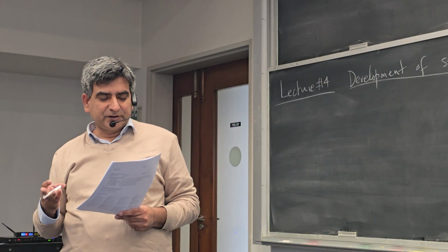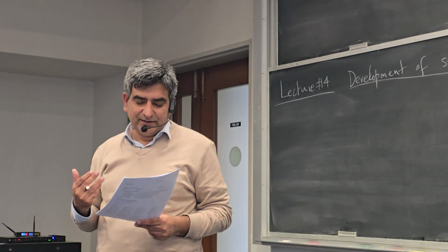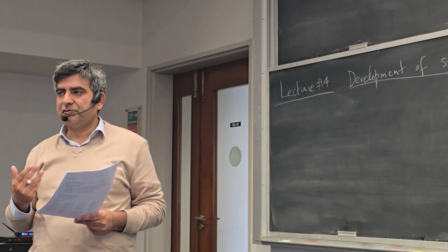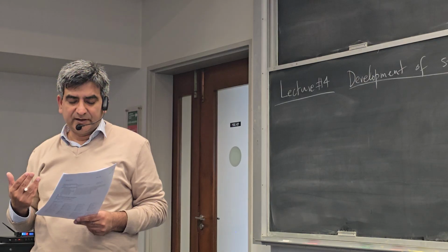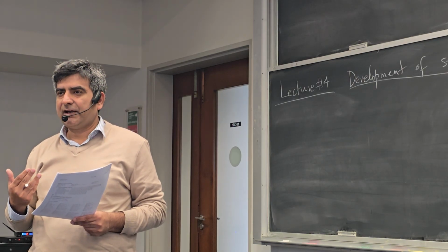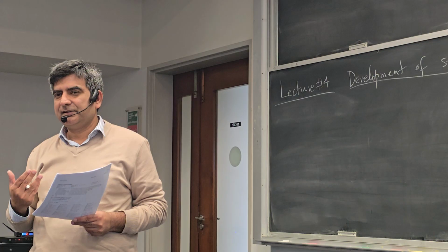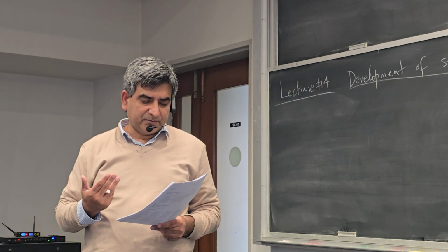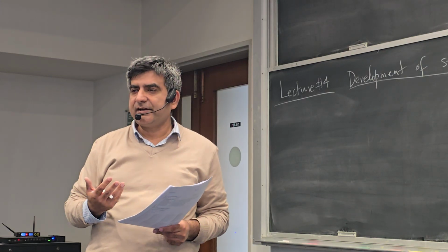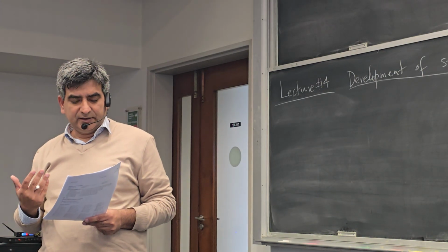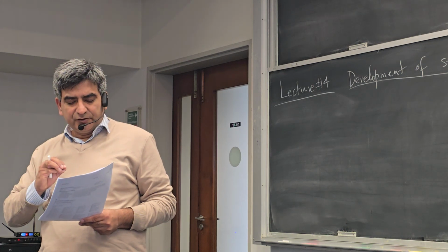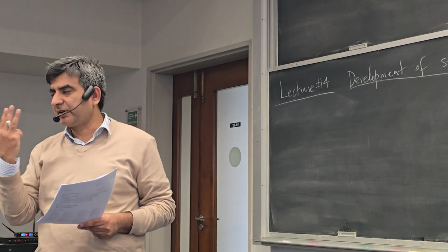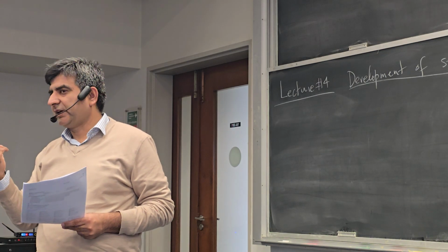Alright, so the difference between P2 and P21 is that P2 is primitive, it has a 2-fold axis of rotation. P21 is also a primitive lattice, but instead of a 2-fold axis of rotation, it has a 2-fold screw rotation. And we're going to learn what that means. C2 is a centered monoclinic lattice with a 2-fold rotation, and so on. So the number of space groups associated with just one point group 2 is 3 for this monoclinic case.